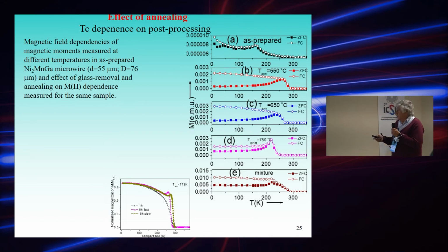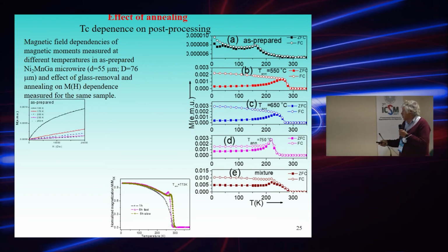One more interesting feature is that the Curie temperature of the materials is affected by the annealing, by post-processing conditions. For example, all as-prepared samples present quite low Curie temperature and irregular temperature dependence of magnetization. But if you anneal the samples, you can achieve Curie temperature near room temperature, and magnetization curves depend very much on the annealing conditions. And just to show the possibility, we mixed different samples annealed at different temperatures, and we achieved broadening of the phase transition. This is a second order phase transition near room temperature, which could be one of the possibilities to use this property of the materials.